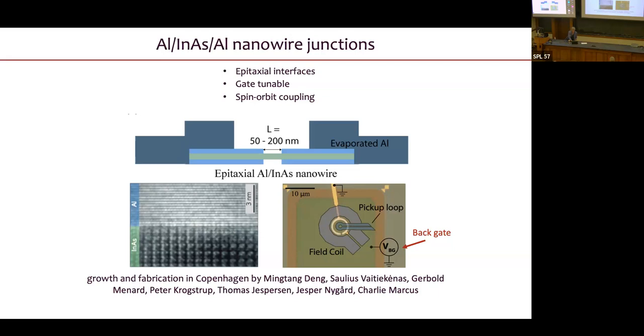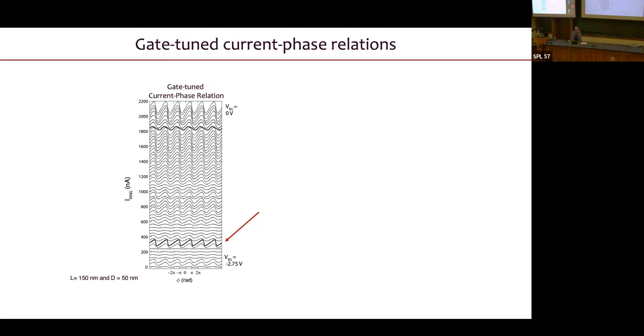And what we find as we gate tune the semiconductor is that below a backgate voltage of -2.75, we don't see any current. I'm showing you the current in the ring as a function of the phase that we've applied to the junction across the ring. Below this backgate voltage, we see nothing. It's just flat, flat, flat. That's because there are no carriers in the semiconducting nanowire at that low of a gate voltage.